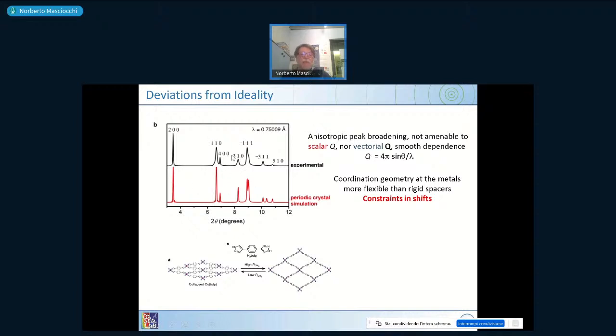So why does this happen? You have an anisotropic peak broadening, which does not depend on the length of Q, which is moving horizontally on the scale. It does not depend in a vectorial way on the Q value, that means on the indices here, but should be related to a coordination geometry, which is somewhat flexible. We need then to develop a model for this system.